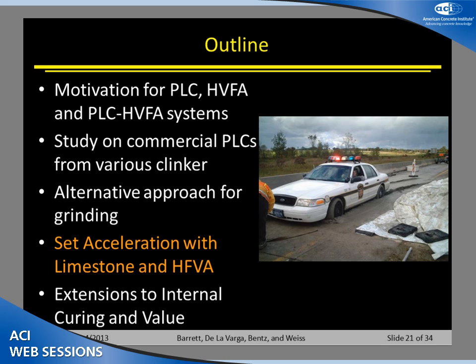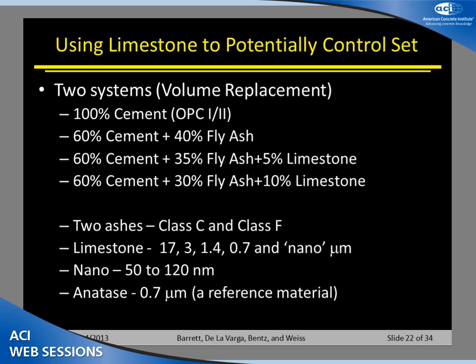The other thing that we've looked at a little bit, and this has been some work that we've done with NIST, is really looking at set acceleration with limestone and fly ashes. One of the things that we looked at when we started looking at high volume fly ashes was the potential concerns that come up. We'd really like to use higher amounts of fly ash, but we don't know when it's going to set. It's going to have slow strength development at early ages. So that's really some of the work that's gone into this.